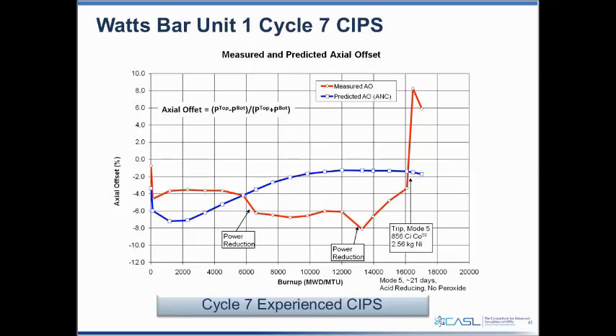When it dissolves out, and then when you return to power, it reprecipitates. But now it has a higher boron-10 content, corresponding to what was in the coolant of boron-10. So you'll see that step change there after the power reduction, which is still expecting to have the same mass of boron in the crud. It just has a little bit more boron-10 in it now.